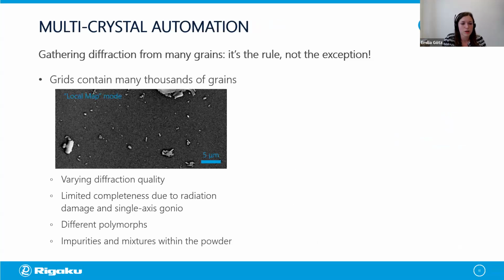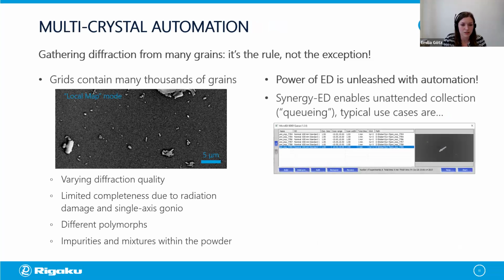And in order to keep this process easy and fast, the measurement can be automated. So this is really where the true power of electron diffraction is unleashed, is if you automate your machine and your data processing as much as possible. The Synergy-ED has a feature for that. It's called a queue, which allows you to set up measurements in advance, which will then be run in an unattended way.